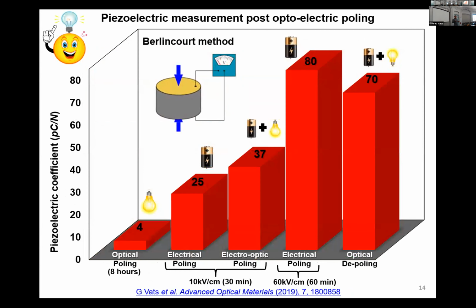I also did the same measurement macroscopically to avoid any confusion. So I had a sample which was not poled. I kept it in white light, like the white light in the room, for 8 hours, and we got a little bit of a piezo response from the material. That means the material was poled.